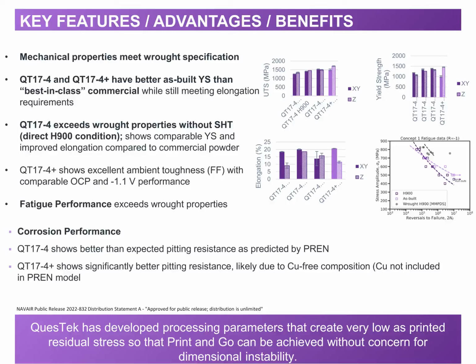material. Corrosion resistance is better than expected, with pitting resistance as predicted by the PREN test, and the 17-4 Plus shows significantly better pitting resistance from the same test against wrought 17-4.